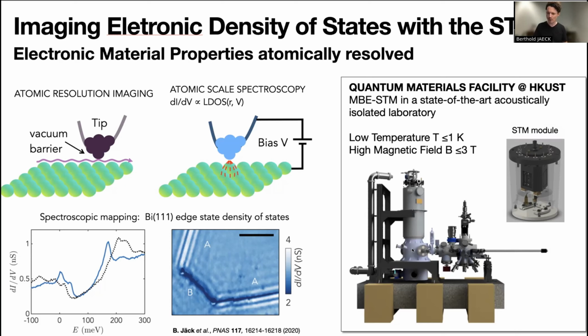The advantage of this approach is that we can grow a sample and essentially study its surface within an hour after deposition. And this is actually quite nice because it facilitates a very fast turnaround time, which, as many of you may know, is quite essential to make efficient progress. From the specs, it's essentially situated, I believe, at a sweet spot. It can operate just below 1 Kelvin using a Joule-Thomson cycle, and also allows us to apply, I would call it, a sizable magnetic field for studying vortex lattices, spin polarized measurements, and so on.